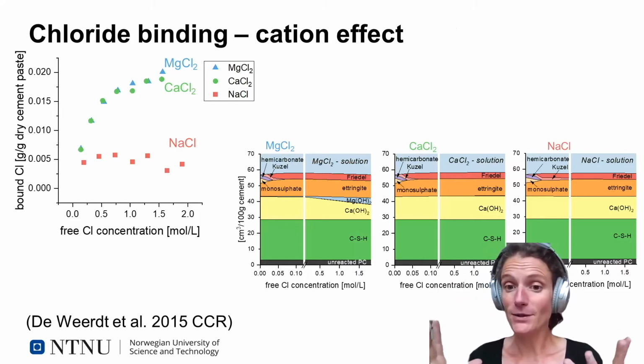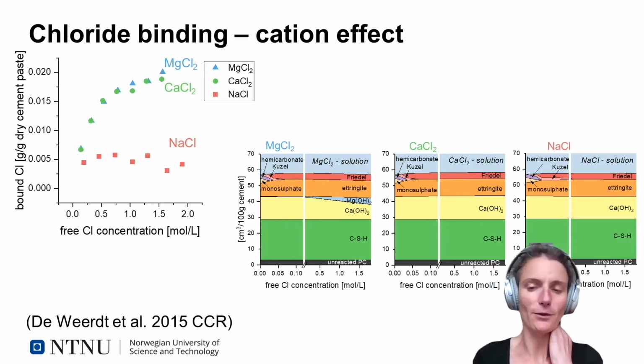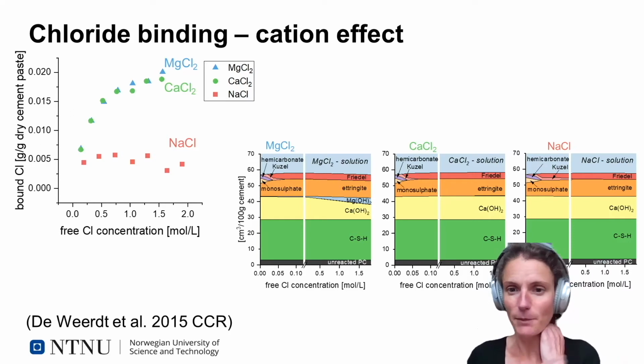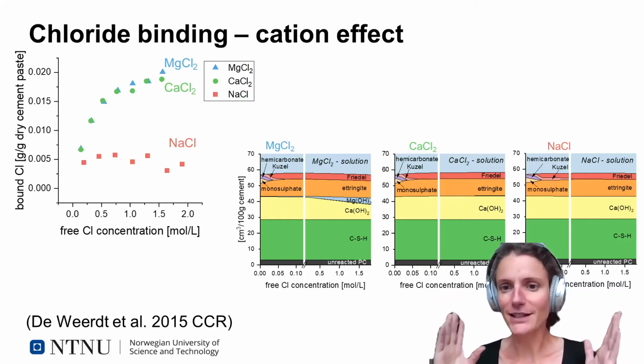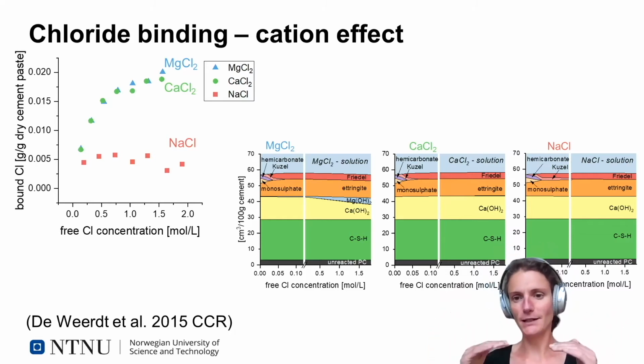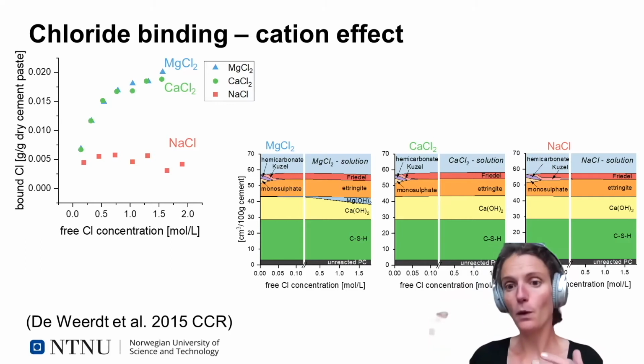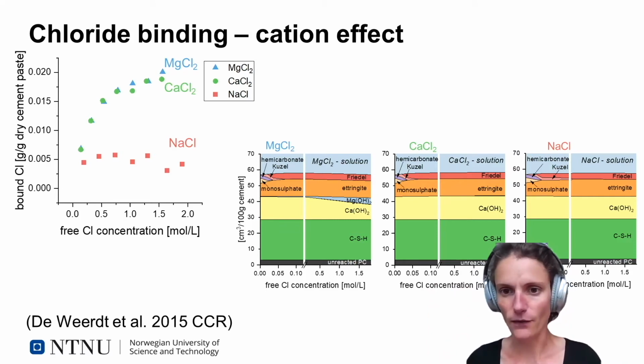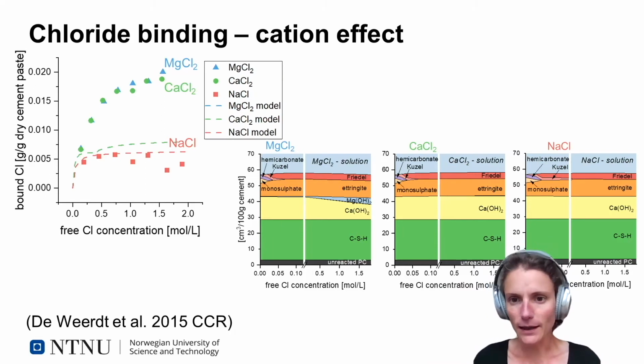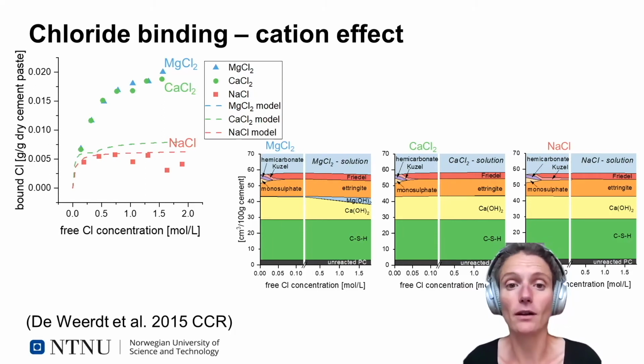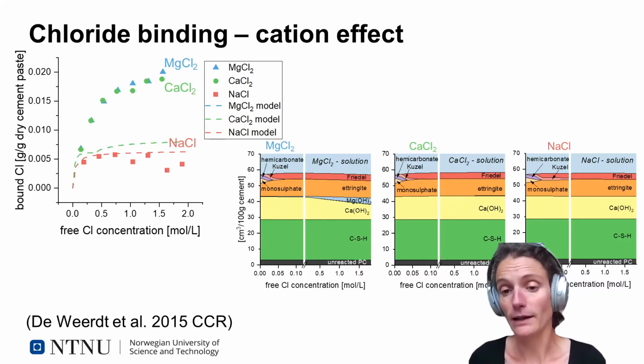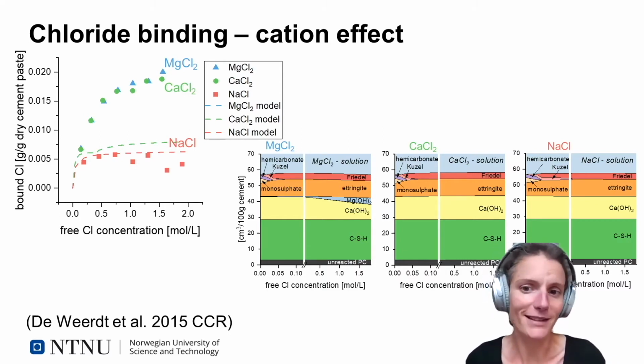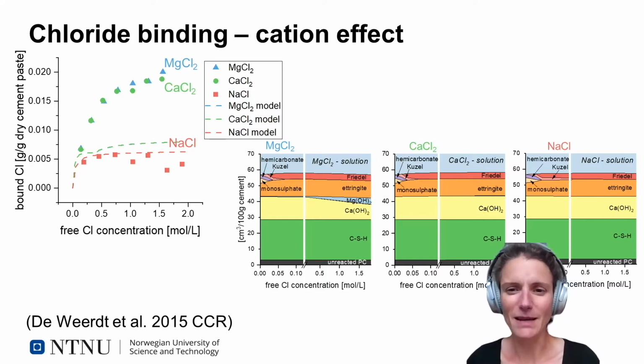So we used a thermodynamic model to predict what was going on in the system. So we used GEMS. I'm not going to go into detail on these figures, it would take us too long, but these figures actually illustrate what the thermodynamic model does. It predicts the hydrate phases that are formed in equilibrium with a solution. So it calculates the composition of the solution and the amount and composition of the hydrates formed. And if we look at the binding isotherms that the model predicts, there's actually not a large difference between sodium chloride and calcium and magnesium chloride. They're rather similar. So the thermodynamic model is not able to capture the difference we observe experimentally.